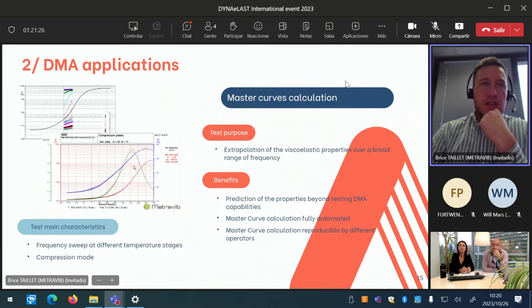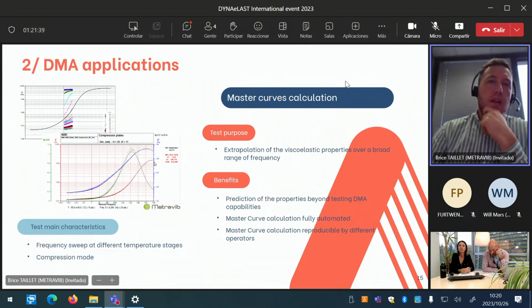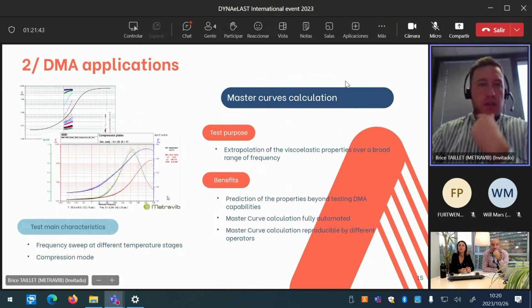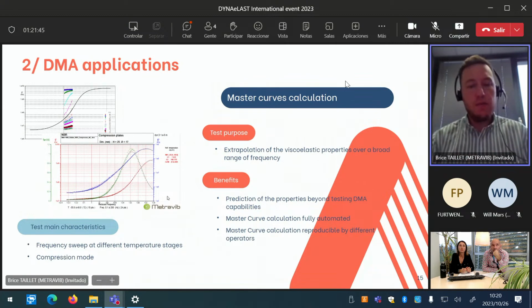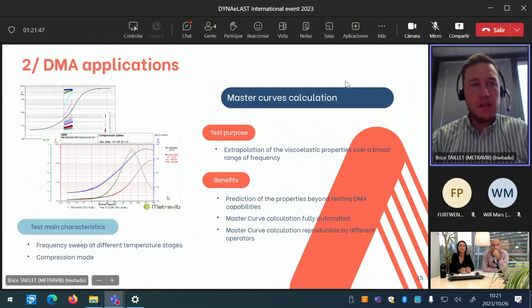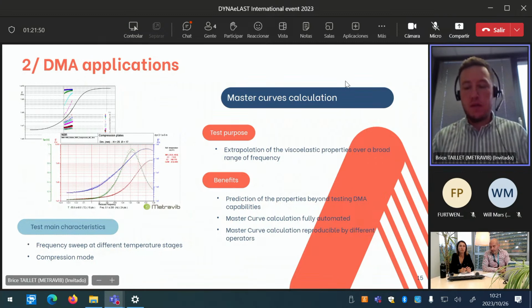Okay, so this example is the evolution of E prime, E double prime and tangent delta as a function of reduced frequency. And here, for instance, you have 1 kHz, 10 kHz, etc., with the WLF coefficients named C1, C2. It's all about theory, but we have a total and automatic algorithm to do it quite easily.